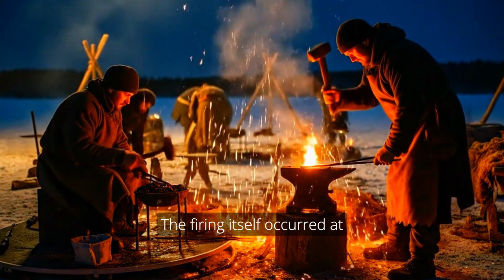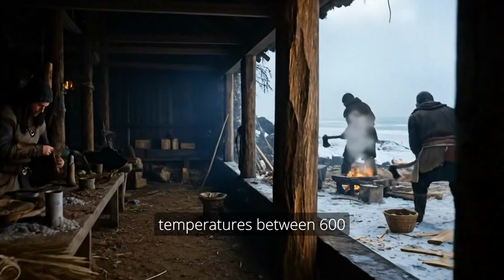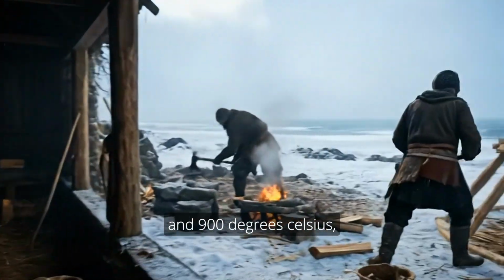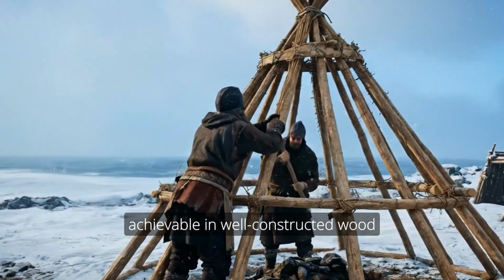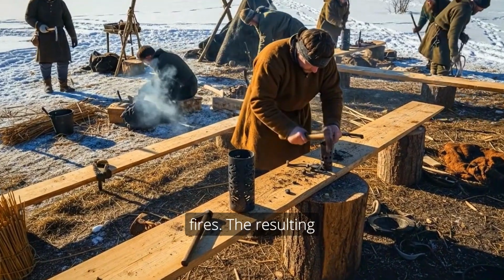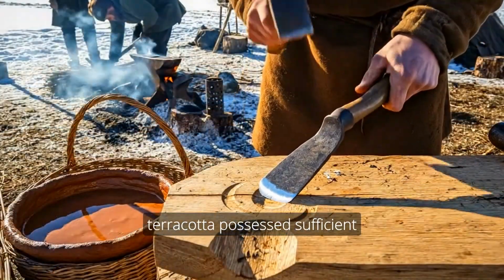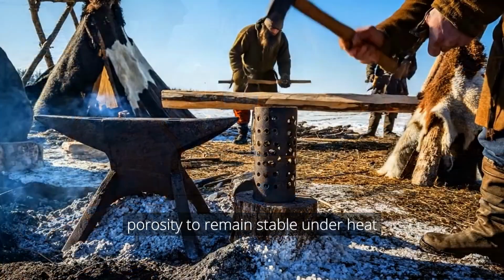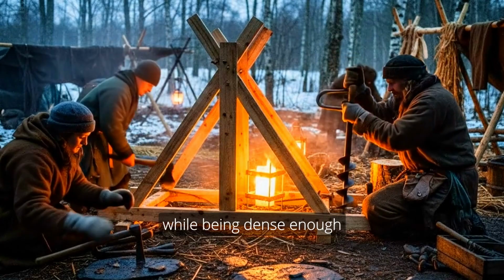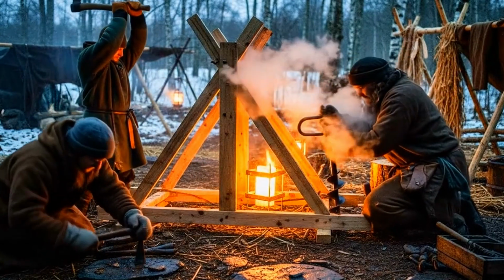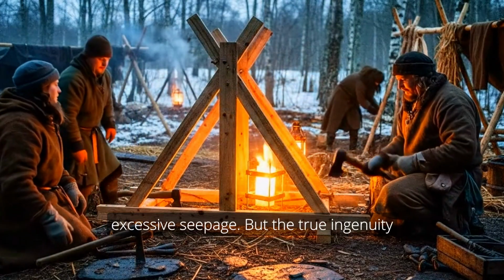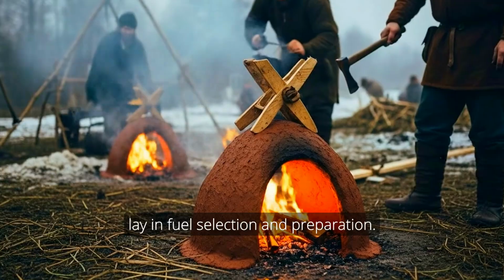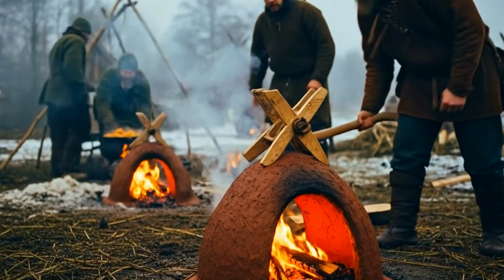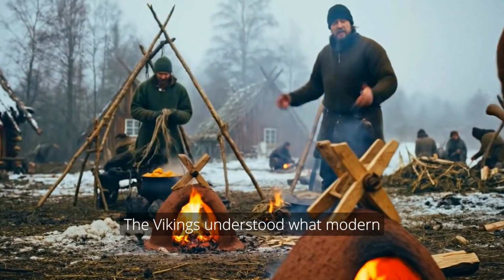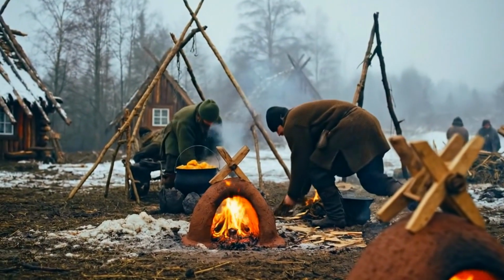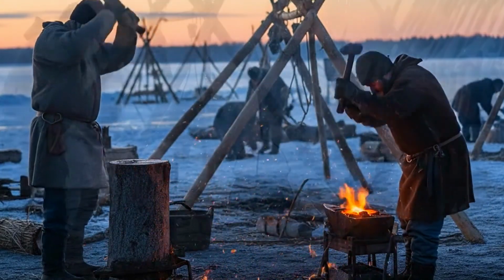The firing itself occurred at temperatures between 600 and 900 degrees Celsius, achievable in well-constructed wood fires. The resulting terracotta possessed sufficient porosity to remain stable under heat while being dense enough to hold liquid fuels without excessive seepage. But the true ingenuity lay in fuel selection and preparation. The Vikings understood what modern chemistry has confirmed. Not all fats burn equally.